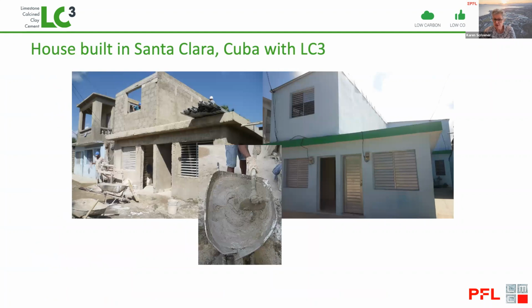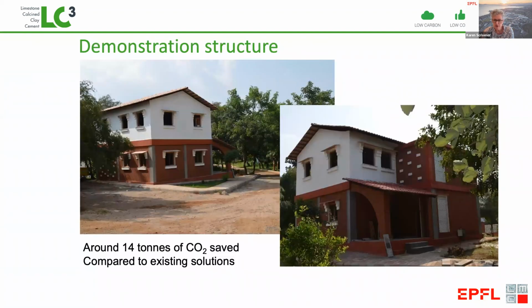This is not just a nice idea in the lab. We've already taken it to full scale. First, we did this in Cuba, and here you can see the house we built in Cuba. These blocks are made from LC3, and also this render to coat the surface of the house is also made from LC3. And this could be used by the workers with no training, no noticeable difference with the existing product. This is the second house we built in India, and we could demonstrate that this could save over 14 tons of CO2, even compared to existing fly ash solutions.